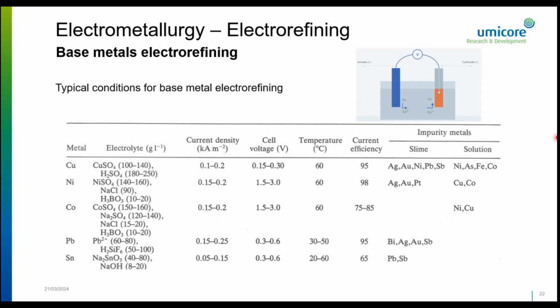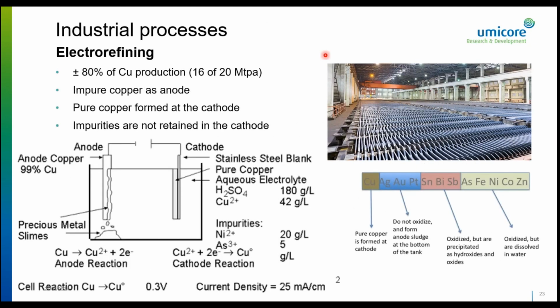So if you look, for instance, at the next slide, here we have also a tank house with the electrorefining tank house. About 80% of copper is produced in this way. These numbers are not completely correct anymore, but 80% is produced in this way, and about 20% is produced by electrowinning. This has to do with the feedstock, the form in which copper is present in the feedstock, if you choose one or the other process. As I said, it's a way to actually extract the metal from an impure material.